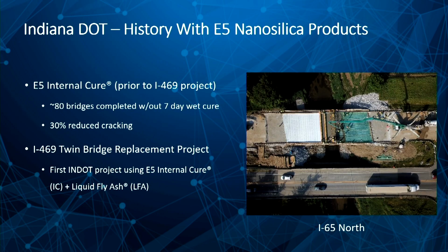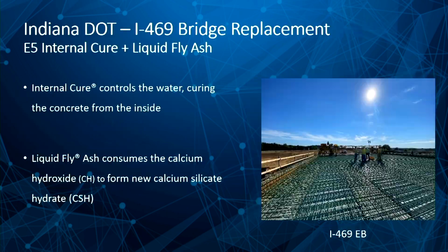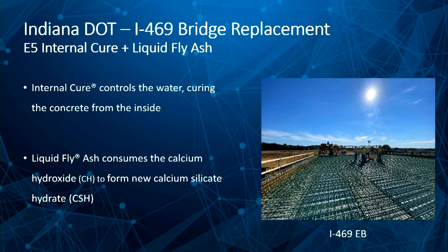With the I-469 twin bridge replacement, this was going to be the first project where they actually used both the liquid fly ash and the internal cure product together. They both have individual benefits, both to fresh and hardened properties. So the internal cure, what's it do? It controls the water, right? It cures the concrete from the inside out. These are Dr. Jason Weiss and Dr. Na Lu's words. They've done years of research on these products and they firmly stand behind them. The liquid fly ash actually consumes the calcium hydroxide to form new calcium silicate hydrate in existing concrete.